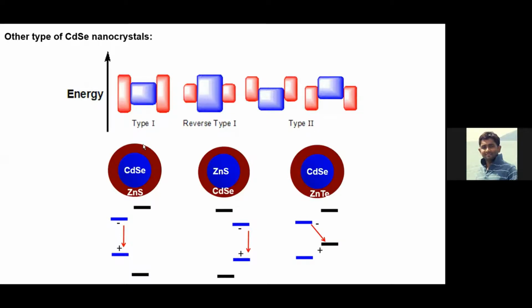Now, as I told, we have different types of quantum dots. This is type 1. That means we have a core and shell. You can get a shell from different semiconductors. So you can make a shell which has a higher band gap than the core. If you take cadmium selenide and a zinc sulfide shell, it's type 1.